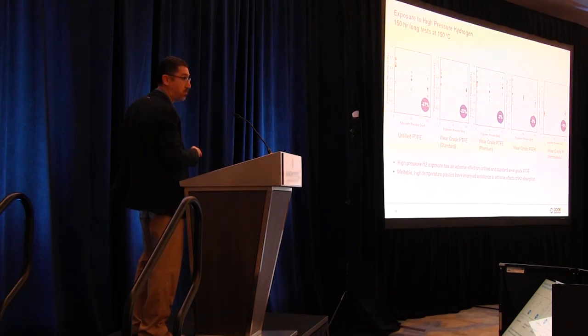So we also did some exposure testing at high pressure hydrogen with several of these materials. And on these plots, I'm showing the results from compressive modulus at different pressure levels. So you have the before tests here. You have 50 bar exposure tests for a 150 hour long test at 150 degrees C, and 100 bar test in this range. So for the filled PTFE, you can see the compressive modulus before and after test drops by about 37%, which is very significant.